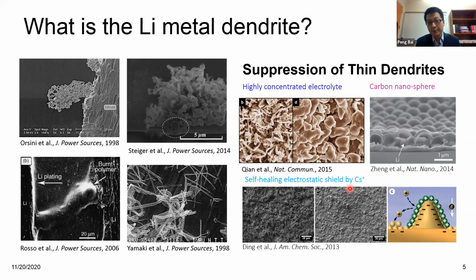And the third approach is really to add additives. Here, this work is adding cesium ions. And you can see here, because it has a different redox potential, it can preferentially be attracted onto the tips of the lithium dendrites, so that incoming lithium ions will be diverted to the valleys. So eventually, when you compare to the one without additive, the surface becomes more smooth.